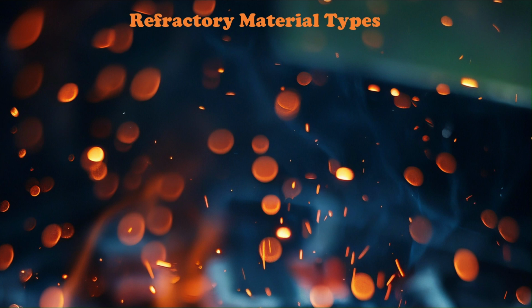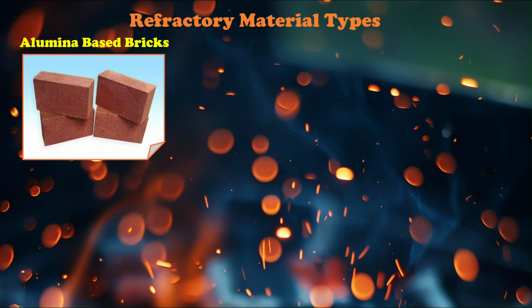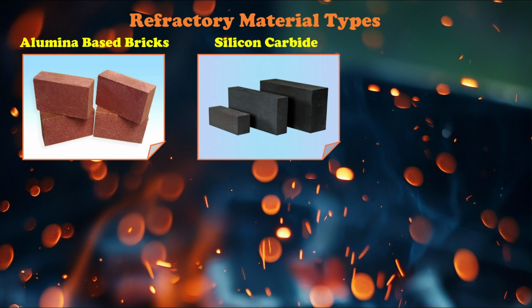The main materials used in the refractory lining of a blast furnace vary by furnace zone but generally include: High alumina bricks, 42 to 62% alumina. Used in critical zones such as bosh, tuyere, tap hole, and lower hearth for their high refractoriness, mechanical strength, and resistance to chemical attack. Silicon carbide and its composites. Increasingly used in the belly, bosh, tuyere, and tap hole areas due to superior abrasion resistance, thermal shock resistance, and chemical stability. These materials are often self-bonded or tar-bonded.